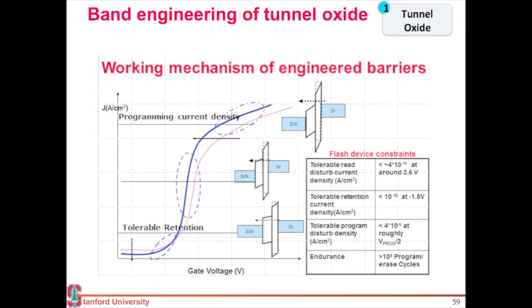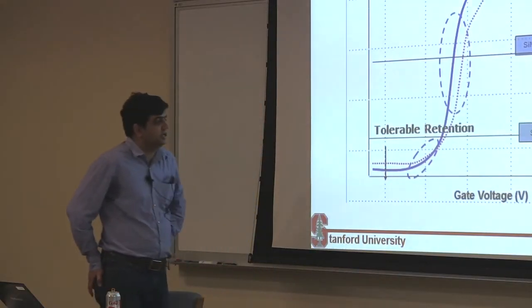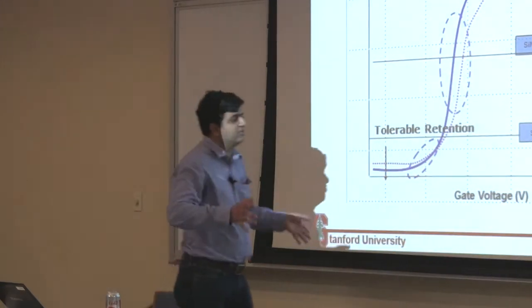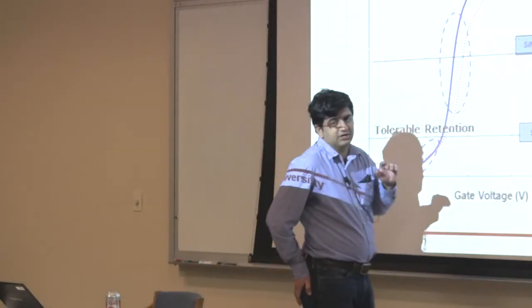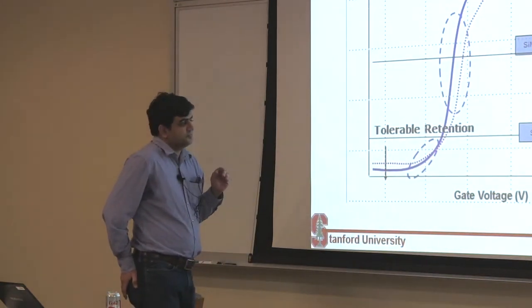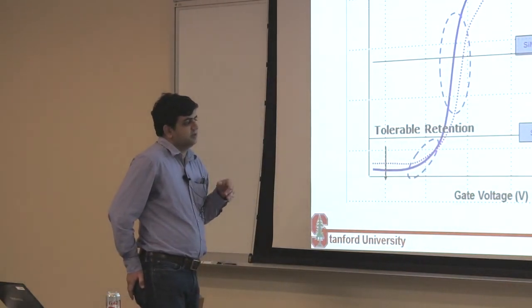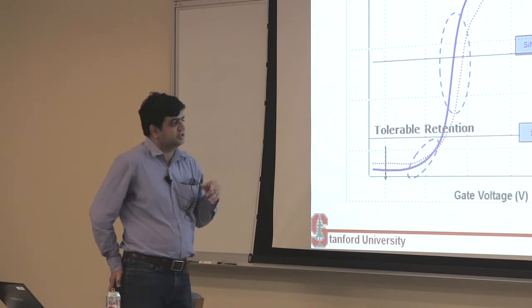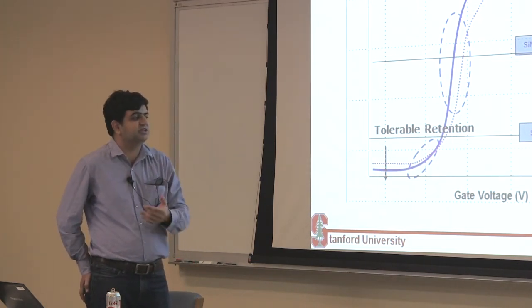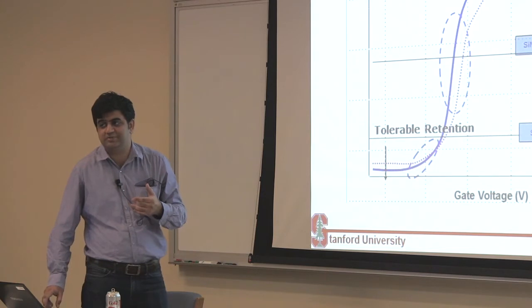But nothing has gone into production yet, because the high quality of this oxide is key — it's the oxide through which your electrons will tunnel in and out more than 100,000 times. If you develop traps in it, you'll degrade your retention and close your program-erase window. That's why people have changed everything about the cell but haven't changed the tunnel dielectric, because anything you replace silicon oxide with fails to meet your retention requirement.